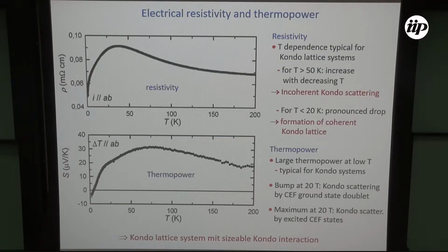The next step you do for such a system is look at the electrical resistivity, because that will immediately tell you whether the 4f degrees of freedom interact with the conduction electrons or not. If they do not, you get the resistivity of a normal metal, boring. If you have a strong interaction, then you get strong temperature-dependent scattering, and that's the typical result you observe. The resistivity increases with decreasing temperature, logarithmically, indicating the onset of incoherent Kondo scattering. Then you go over a maximum, and you get a strong decrease because the Kondo ions form a coherent state. So that is the first very clear indication that we have a strong Kondo interaction, and a low temperature formation of a coherent Kondo lattice.